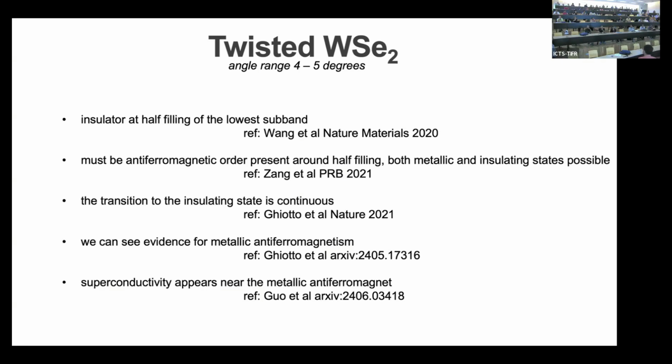At lower twist angles, you do see ferromagnetism appear. So ferromagnet phases are not far away from this. And Xiaodong has some data on ferromagnetism at lower twist angles. But at these twist angles, there's no evidence of ferromagnetism from optics. And there's no hysteresis seen in transport. Now, ferromagnetism by itself would do something different to the Hall effect. But this sort of simple picture of the Fermi surface reconstruction would not be the same in a ferromagnet. So it's all circumstantial from the perspective of transport. The only concrete thing is we don't see any hysteresis in transport.